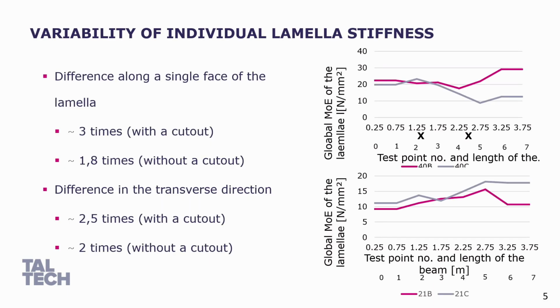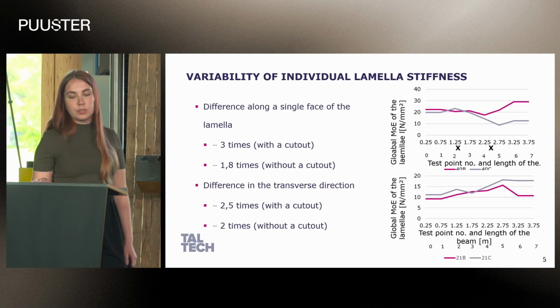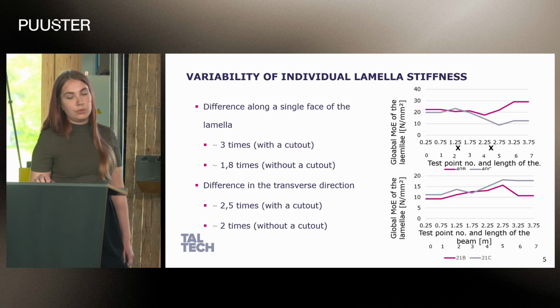These 2 graphs illustrate the individual stiffness variability of 2 lamellas. In the top one, the lamella also had cutouts. The stiffness of the lamella was affected by different defects, such as cracks, knots, and also the cutouts. On one face of the lamella, the largest stiffness difference was approximately up to 3 times, and in the transverse direction at one test point, the largest stiffness difference was approximately up to 2.5 times.